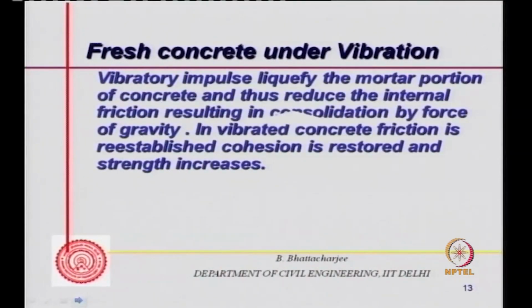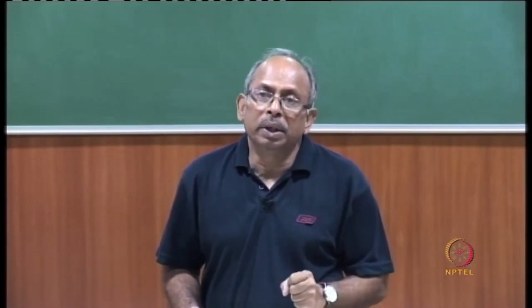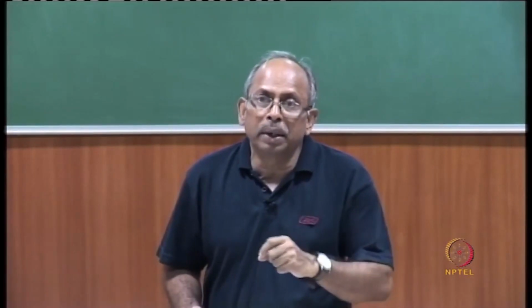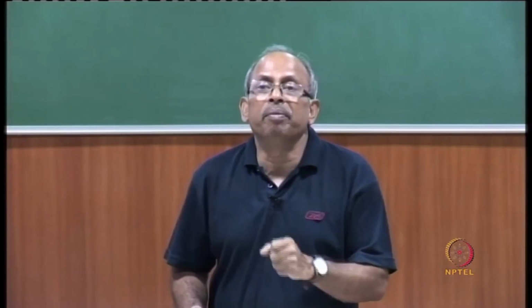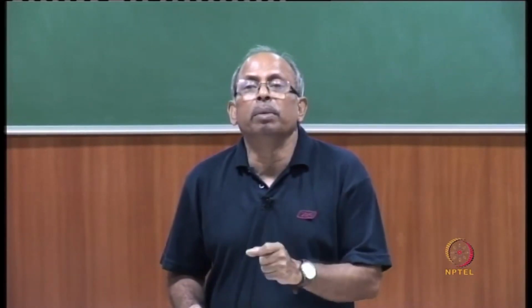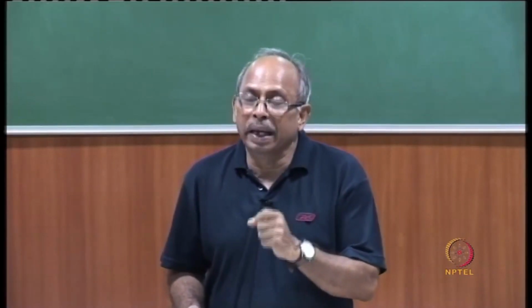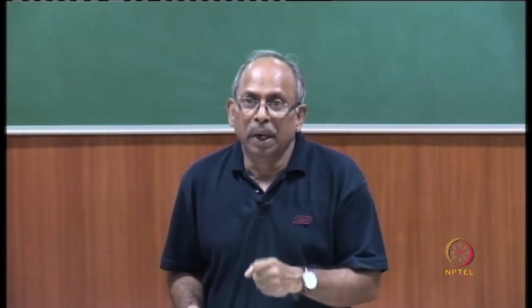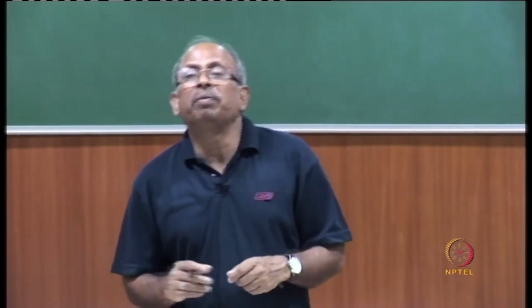So what happens? Vibratory impulse actually liquefies the mortar portion of concrete, and thus reduces the internal friction, resulting in consolidation by force of gravity. Then once the concrete is vibrated completely, the friction is re-established and cohesion is restored and strength increases. Now how does it occur? Vibratory impulse essentially causes the water in the paste system to vibrate more, which moves more than the solid particles, and the more constricted the necks are, it will exert more pressure, and this pressure actually overcomes the friction, resulting in a kind of collapse of the system.